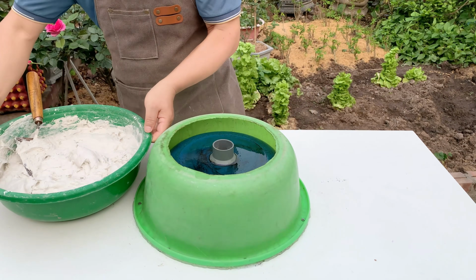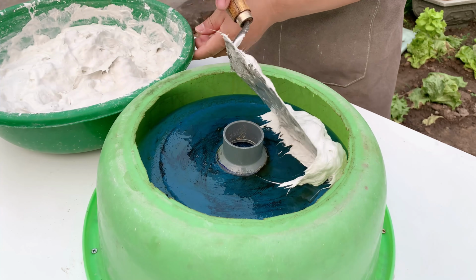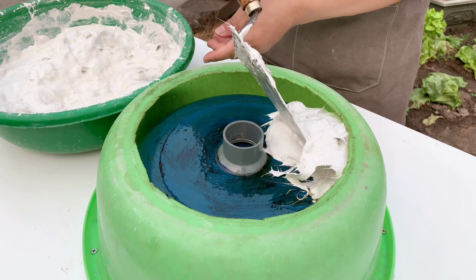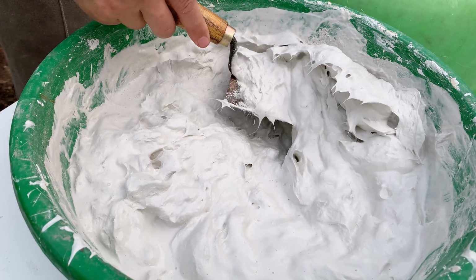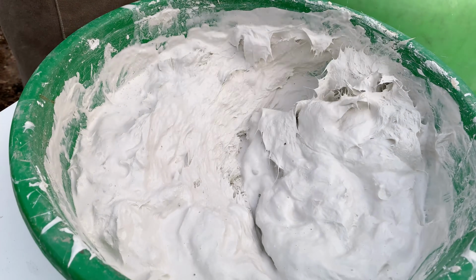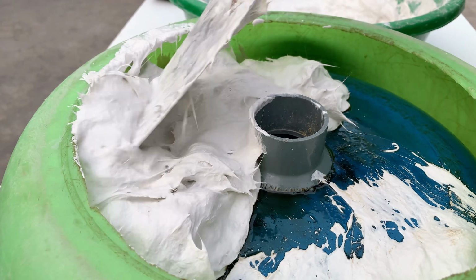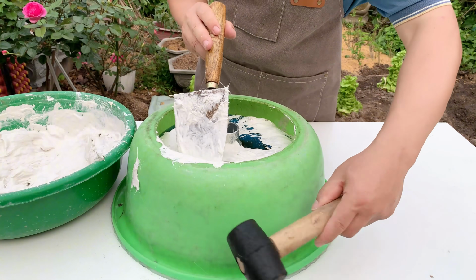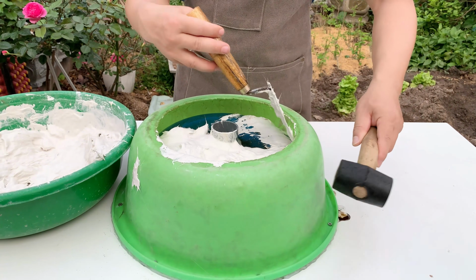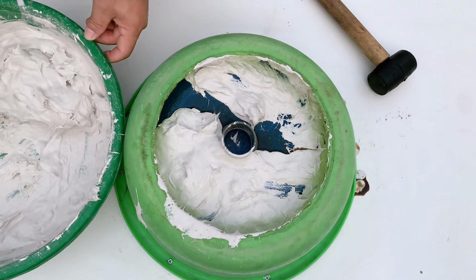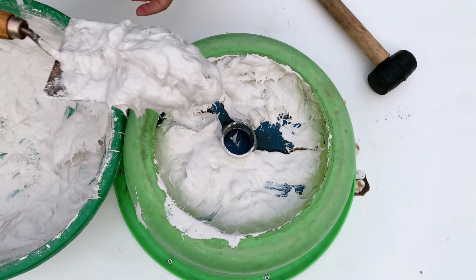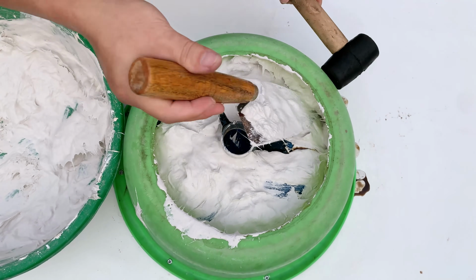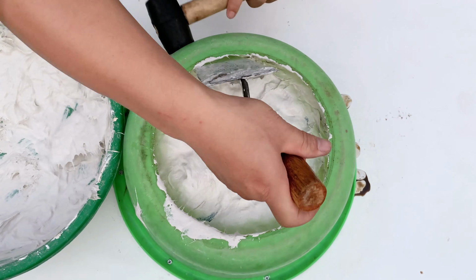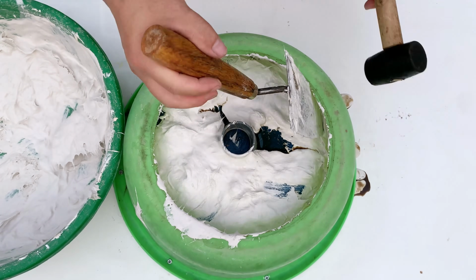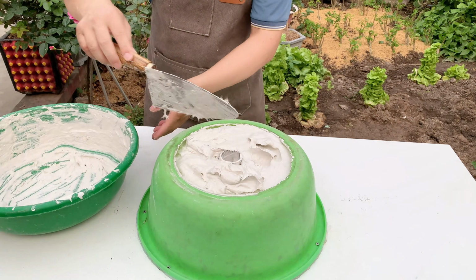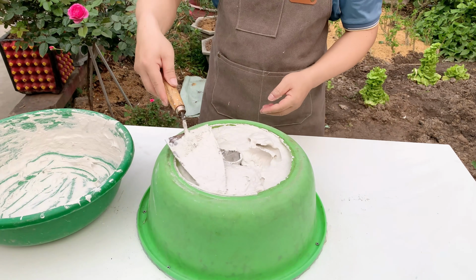And now comes one of the most important stages in the entire project: pouring the mold. The mixture gets poured slowly into the gap between the two basins. Then we begin tapping the mold gently from different directions. This process helps trapped air bubbles rise upward before the concrete hardens. And honestly, tiny air bubbles create bigger problems than most people expect. They reduce structural strength and create visible surface holes later.